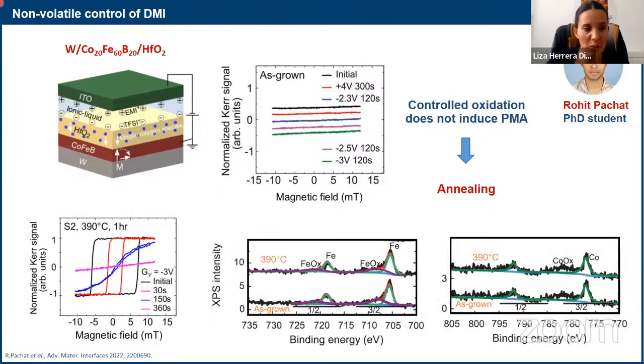So we did that, we got PMA, but what is interesting is that we did XPS on the samples before and after annealing, and we could really confirm that the peaks look the same for iron and for cobalt. So there's really no oxidation here. It's just the effect of the crystallization, just the effect of the annealing. So this shows that there is a transition between in-plane and perpendicular anisotropy that is not related to oxidation. So this is quite different from the system that we saw before.